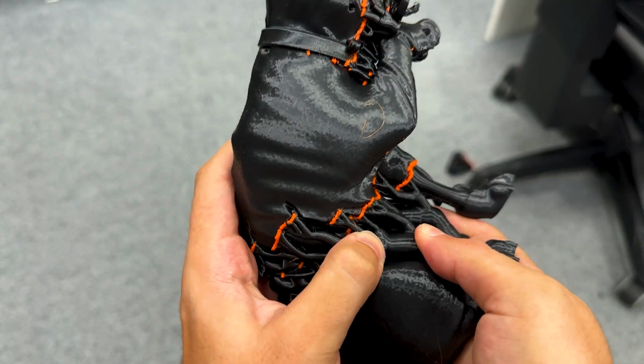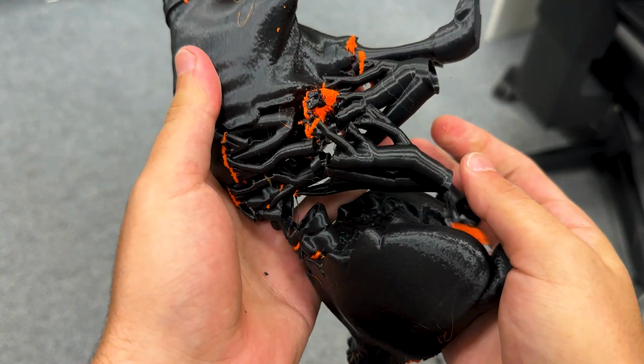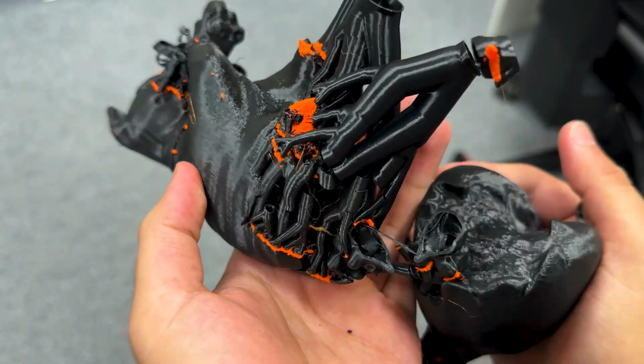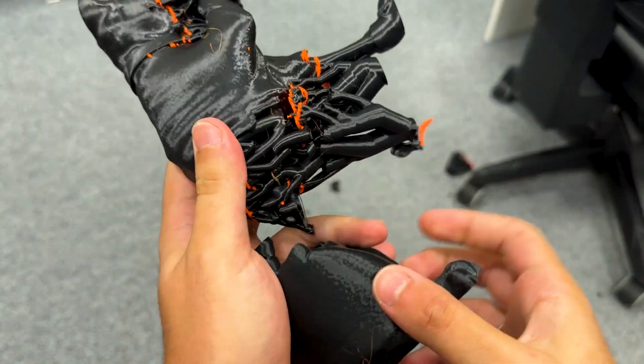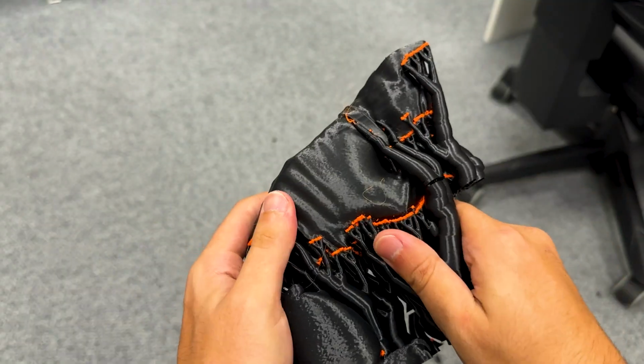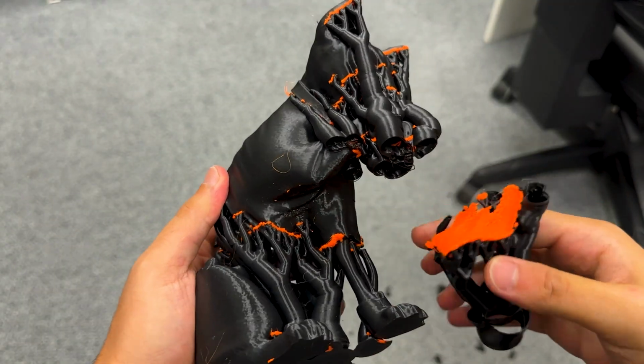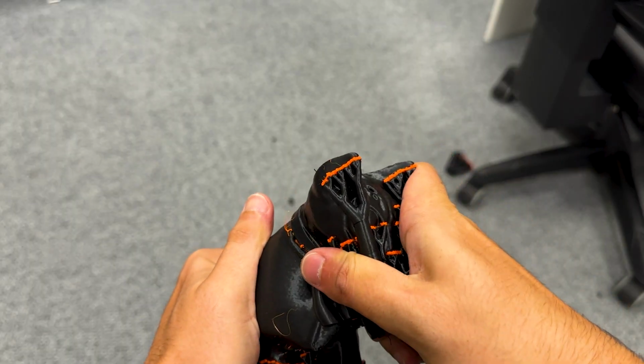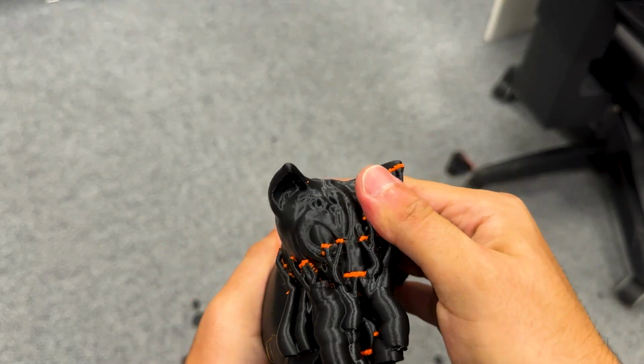But being brittle is also a problem. As you can see, we even broke the print while removing the support. So we noticed that due to it being a single extruder and needing to purge from one material to another, the PETG mixed with the PLA in the print, which compromised the piece's strength.